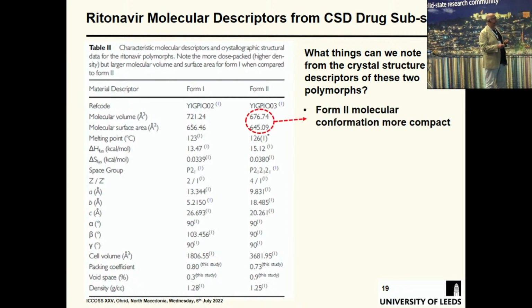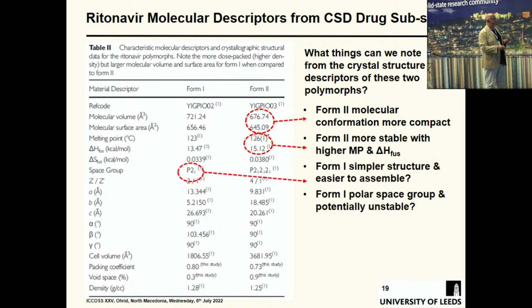First thing you notice about this is that form 2, the molecular conformation, is more compact. You can see from the molecular volume is smaller, the molecular surface area is smaller. Just more compact. It's more stable, so you can see this from the melting point and the enthalpies of fusion. And you see immediately, once you know the enthalpy of fusion, this will be less soluble. So it's fairly obvious stuff. Form 1 is a simpler structure and easier to assemble. Now, that's an interesting thing.